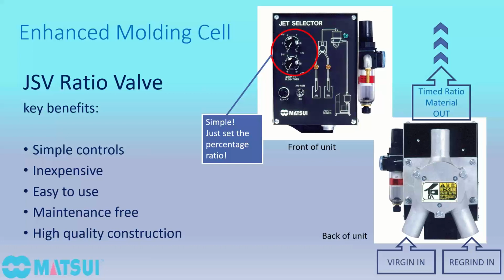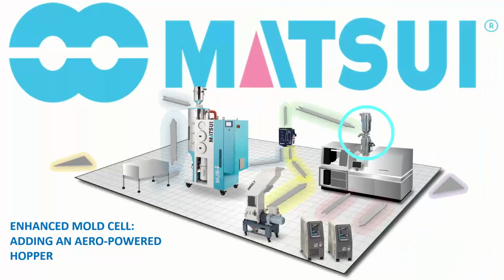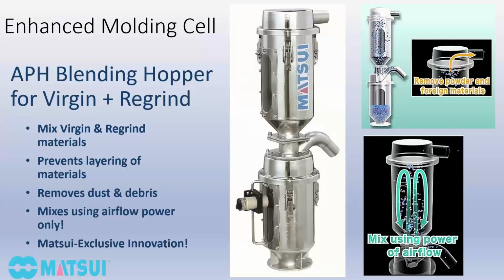So now that we've got the virgin material and the regrind material mixed together, we need to make sure that they're going to mix together properly in the mold. So we're rationing our virgin and regrind material together, and that material is being sent to the injection machine. What you want to prevent from happening is layering of the virgin and regrind material. If the material is layered too much, that means some of your parts might have a higher concentration of regrind than you want, and that can cause those parts to be defective. So you don't want the layering of virgin and regrind material as it enters the injection machine feed screw.